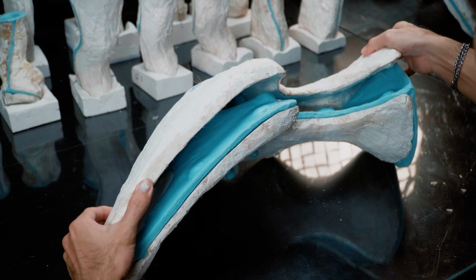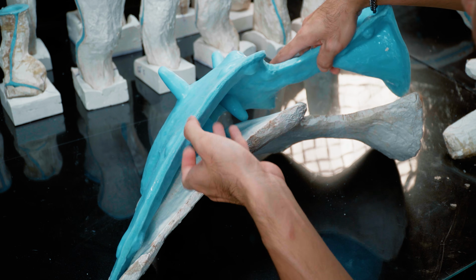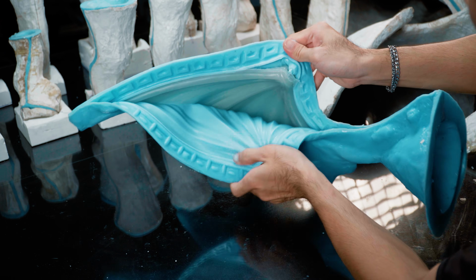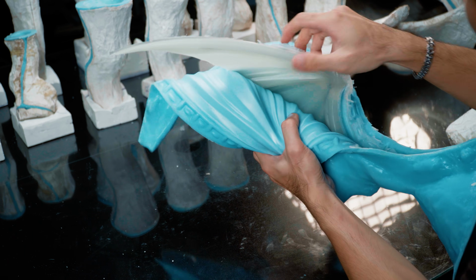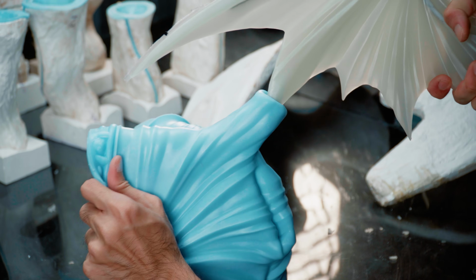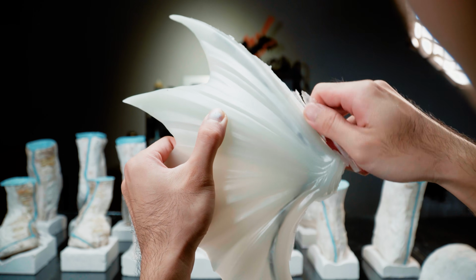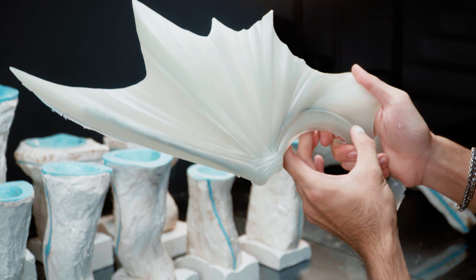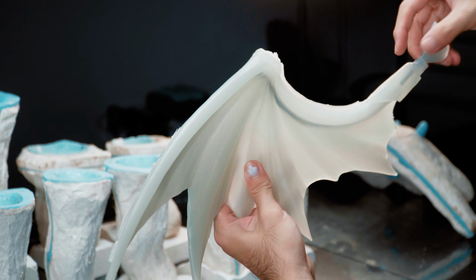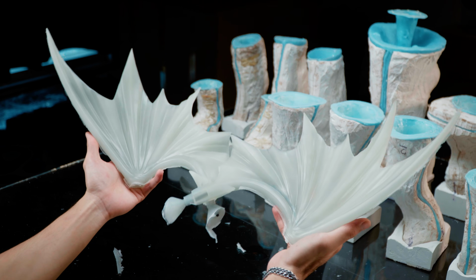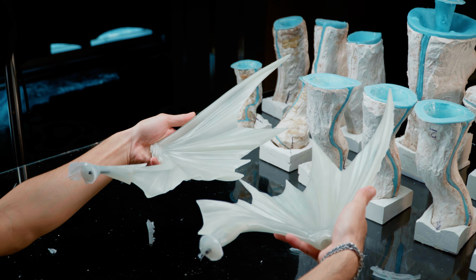After waiting 24 hours, I was able to remove the mold and see the result. It is really perfect. The surface is extremely smooth, without any small defects. Now I will clean up the excess burrs from the mold. It is very thin. Just need to lightly shave and use sandpaper to go over it, and it will be absolutely smooth.